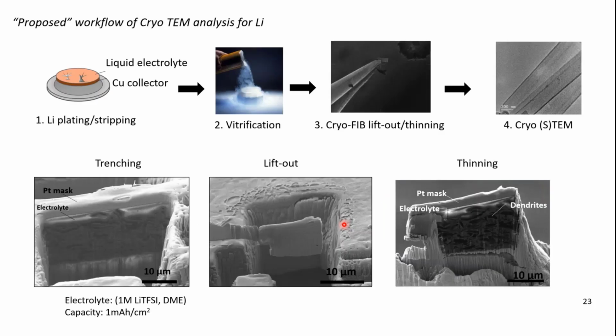So my proposed work is, instead of washing and rinsing excess electrolyte, we can also preserve liquid electrolytes on the copper current collector before you finally freeze it in liquid nitrogen. And once it is vitrified, you can use cryogenic lift-out procedures to thin your samples until you have the desired electron transparency. And once you have electron transmission, you can transfer your sample from the cryo-FIB stage to the cryo-TEM such that you can have high resolution imaging.